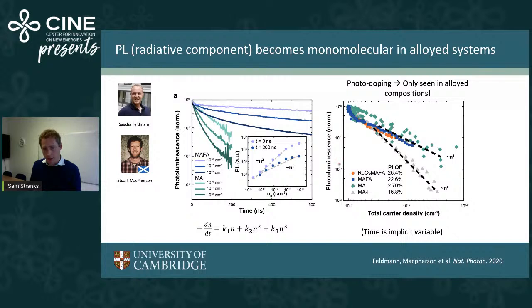This is a plot where we look at the photoluminescence as a function of carrier density. These are from PL decays, but here, as the PL decays away, the carrier density goes down. So here, this is plotting it as a function of carrier density, where time is an implicit variable. And what we see is, if we look at the methyl ammonium lead iodide film, you can see it's second order across this entire charge density regime. And this is what we expect for just a bimolecular recombination.